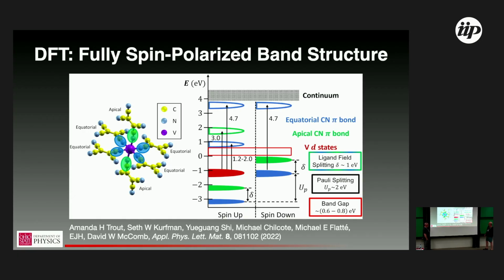Well, if it's a sketch, but it looks like it's not constant, is it? You're saying, why don't we have something that's kind of... Yeah, for instance, between this. What I would say is that this is a sketch that's extracted from the calculated density of states, and it takes a little bit of inference to disentangle. And it's a little hard once you get into these conduction states to really identify clearly. You have less features because it's higher energy, so there are more states with different orbital character that they can go into. The sketch is sort of failing as the bandwidth increases as you go higher in energy.